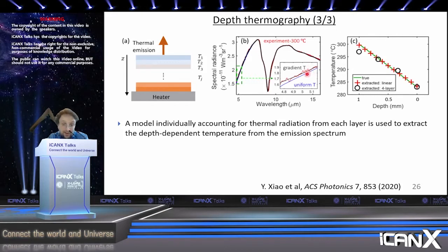There's this delta over here, and you might imagine that this is just an experimental error, but it's actually not, because the fit is really, really good over here at longer wavelengths. What it turns out is that the reason for this discrepancy between the uniform temperature fit and the experimental data is the fact that the temperature here is not the same as the temperature here, and therefore you can't make this uniform temperature assumption and apply the simple form of Planck's law and be able to fit the data.